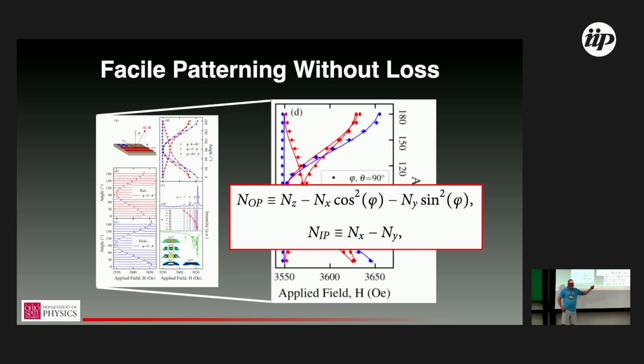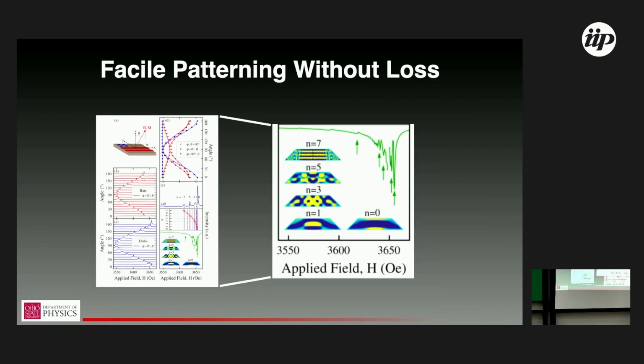So this plus the saturation magnetization will allow you to predict what the mode structure looks like. And this is, again, something I showed on Monday, where this is now using only those fit parameters extracted from this angle dependence, extracting the expected mode distribution, spin wave distribution.